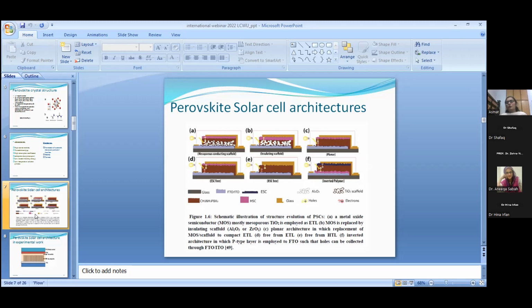And if we move to the planar structure, we have the compact electron transport layer, and we fabricate the perovskite solar cell without the electron transport layer and also without the hole transport layer. There is also the inverted perovskite solar cell architecture, in which the hole transport layer is in direct contact with the FTO, and we can collect the holes from this FTO.